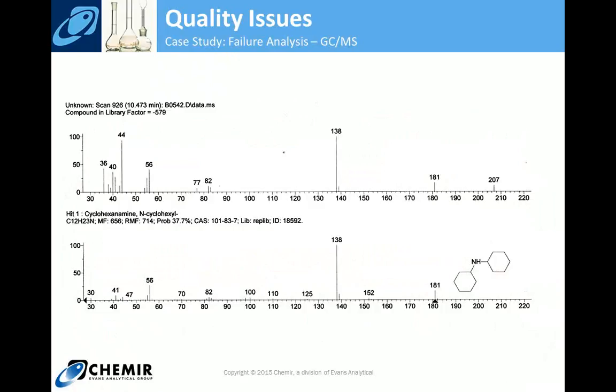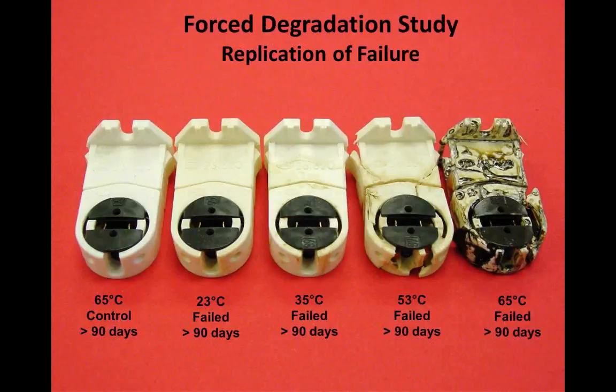but our customer really wanted to confirm, is this truly what's happening? Or is it maybe just a coincidence that we see some dicyclohexylamine, we see aminolysis of the polycarbonate? Maybe it's a coincidence that the DCH is just present on the cracked polycarbonate. So what we recommended, and they approved, is a controlled exposure where we exposed these polycarbonates to dicyclohexylamine, a forced degradation study.